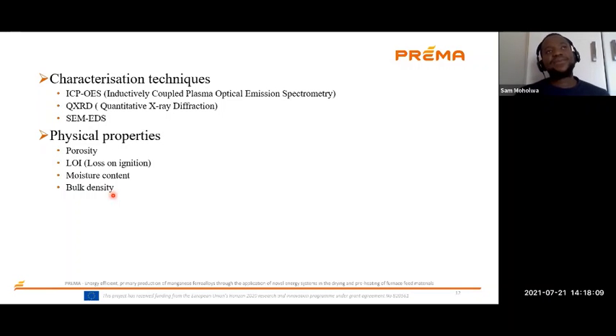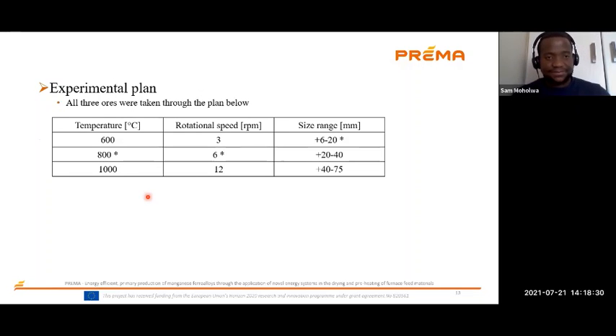Remember, we screened the samples into 3 size ranges, which were +6, -20, +20, -40, and +40, -75 millimeters. So let's say for OA, we determine the bulk density for +6, -20. Then again, we determine the bulk density for +20, -40. Then the same applies with +40, -75 millimeters.